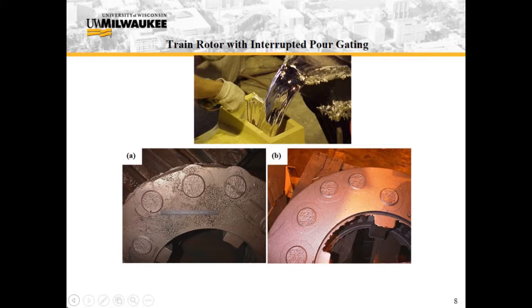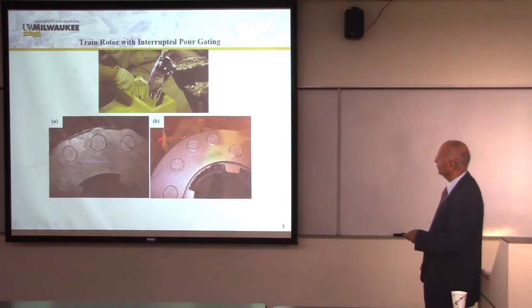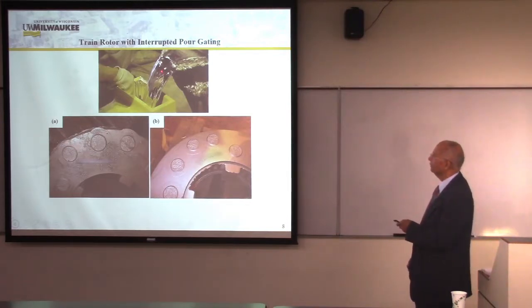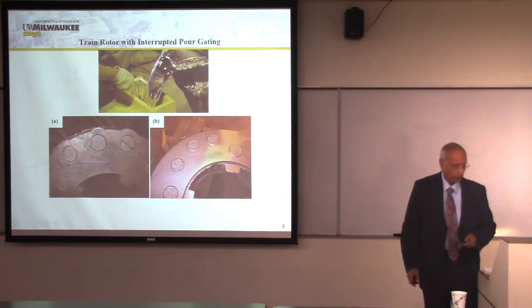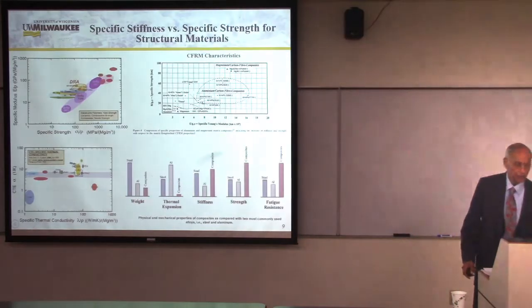Here is an example of a 400 pound melt of aluminum silicon carbide composite. This is the melt which has got silicon carbide particles and aluminum silicon melt. It is being cast into large brake rotors for trains in Germany. To give an example that these composite alloys can be poured like any normal casting that you produce.